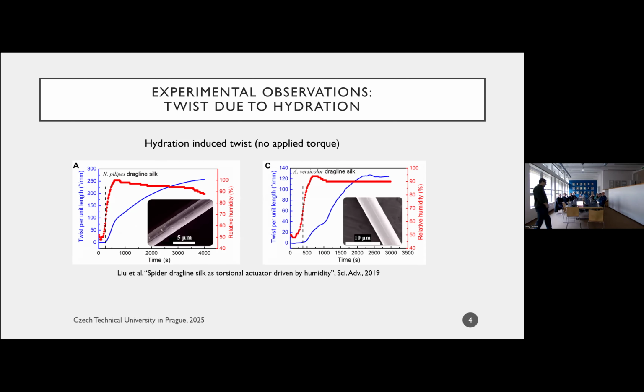And there was another paper. Okay, there was another paper that came out in 2019, so this is fairly recent. What the researchers did in this work is they took a silk fiber. Again, they came up with a very clever way to measure the twist. We'll talk about this in a little bit. But what you can see here, the red curve is the relative humidity. The blue curve is the twist per unit length. And again, as long as I'm below about 60, 65, 70% relative humidity, nothing really happens. But once I pass that point, all of a sudden the fiber begins to twist, and it twists by as much as 270 degrees per millimeter. Right. So this is a pretty significant twist. It's not a small twist.